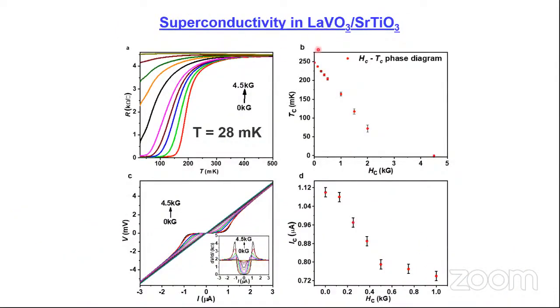So as I said, we discovered superconductivity at LVO-STO interfaces, and the superconducting transition temperature is about 250 millikelvin. And the transition temperature goes down systematically as we increase the magnetic field, which is expected for a superconductor. And the superconducting signal disappears above 4.5 kilogauss, which is the critical field that we measure. And this is the HC-TC phase diagram as we get it from this RT data. We also observe the critical current of the superconductor. And from the critical current data, one can say that this is actually a very fragile superconductor.